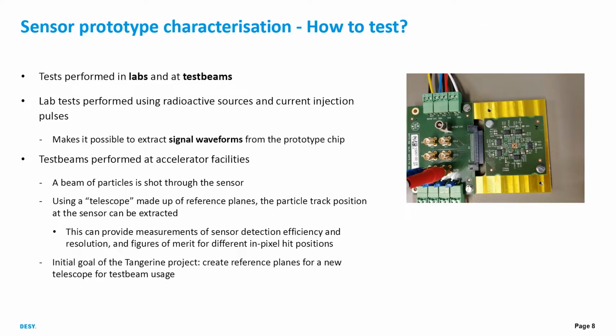Now, sensor prototype characterization. How do we do this? How do we test it? Tests are performed in labs and at test beams. So the lab tests are performed using radioactive sources and current injection pulses. And this makes it possible to look at the signal waveforms from the prototype chip, so we can read out the analog waveforms. Test beams are performed at accelerator facilities, where a beam of particles is shot through a sensor, and using then a telescope, so-called telescope made out of reference planes, we can find the particle track position at the sensor. And this can give us measurements of sensor detection efficiency and figures of merit versus different in-pixel hit positions and so on.